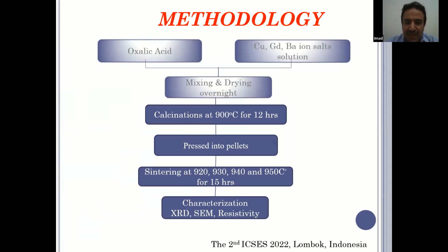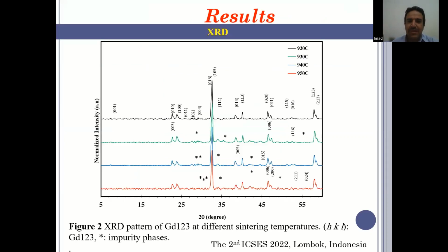and 950 degrees for 15 hours. After that, the sintered pellets are subjected to characterization: XRD, SEM, and resistivity measurements.